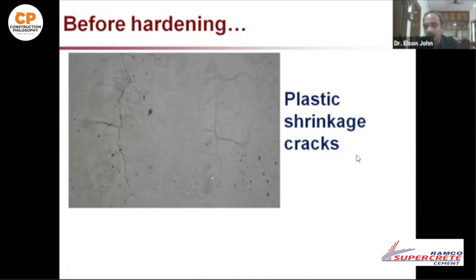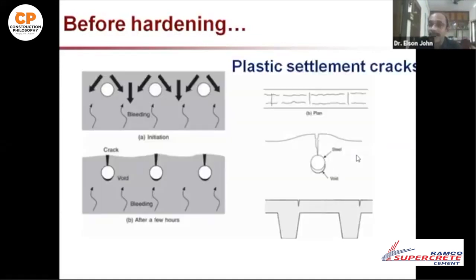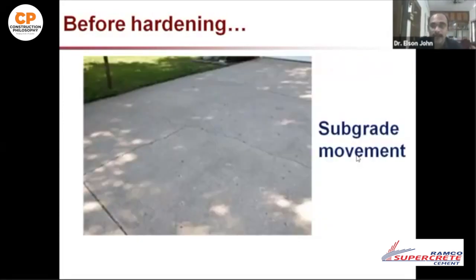So let us see some of the types of cracks and how they occur. Plastic shrinkage cracks can start within a few minutes after the concrete is placed and go up to the initiation of hardening, a few hours. Then we have the plastic settlement cracks. In the first stage, concrete is saturated, so the water will bleed to the top and the solid materials have a tendency to come down. All the other parts except over the reinforcement, the material is free to settle. Above the reinforcement, tensile stresses develop and you can see the cracks.